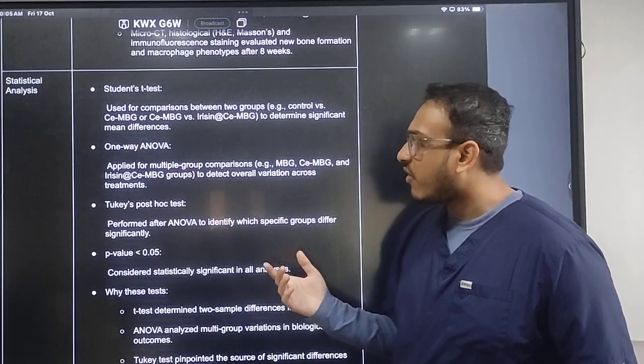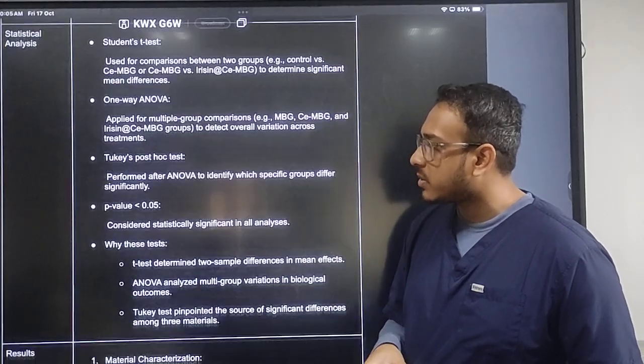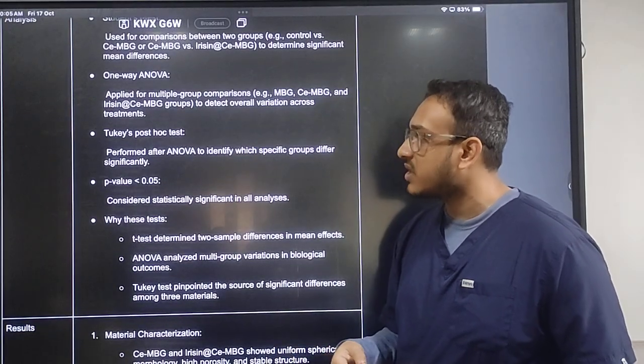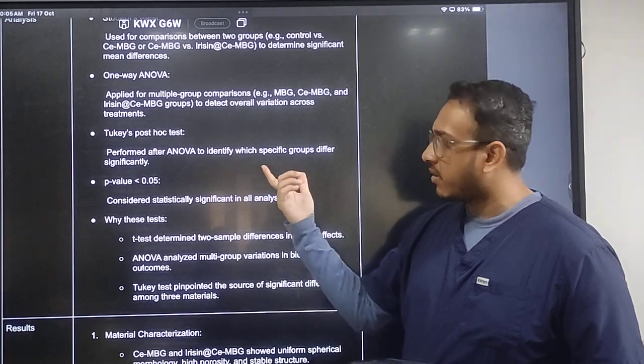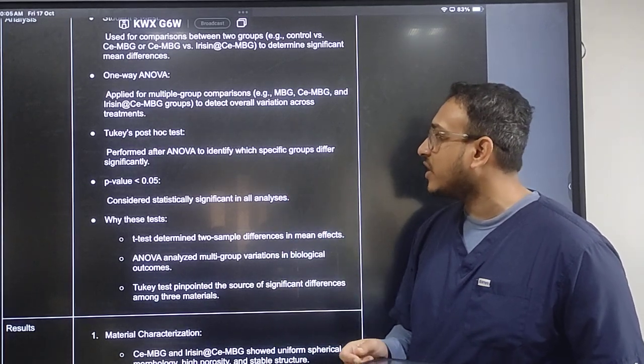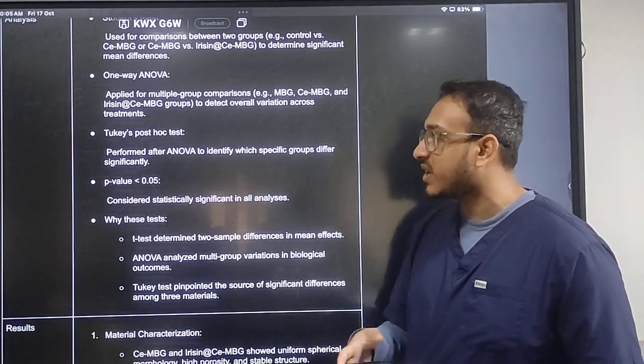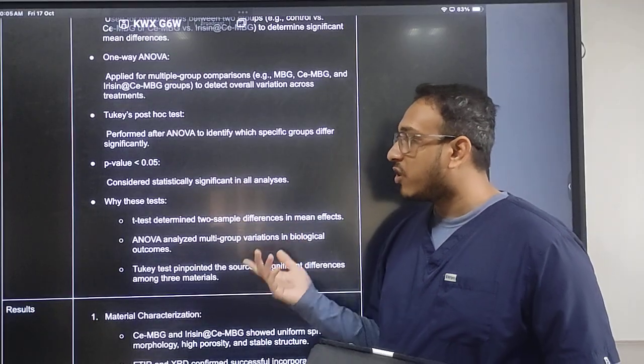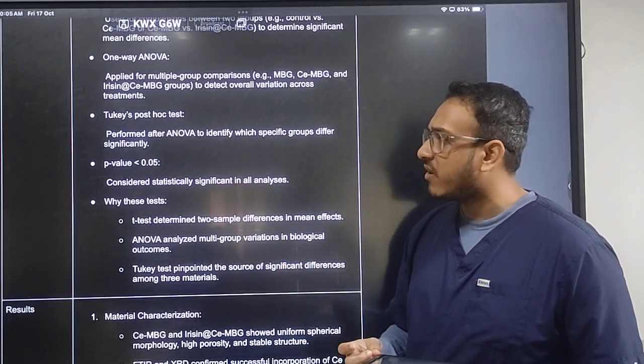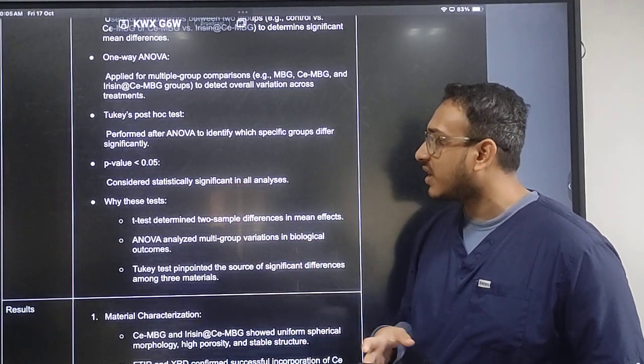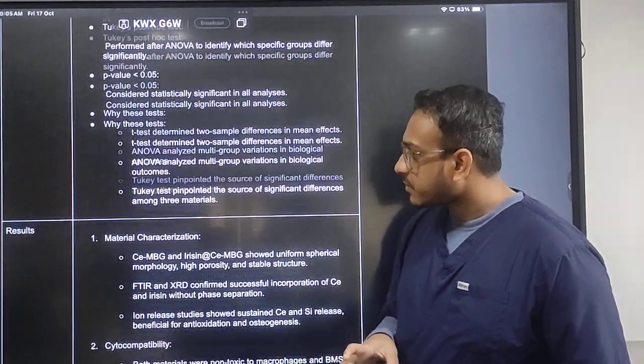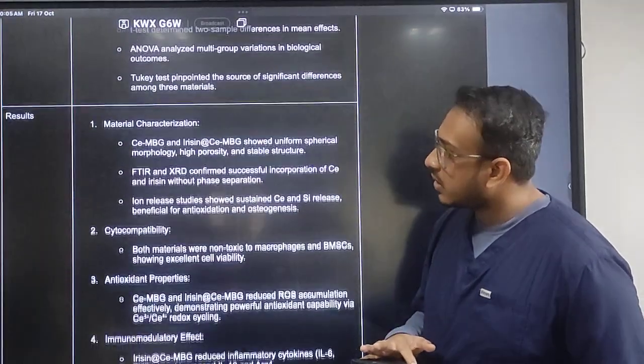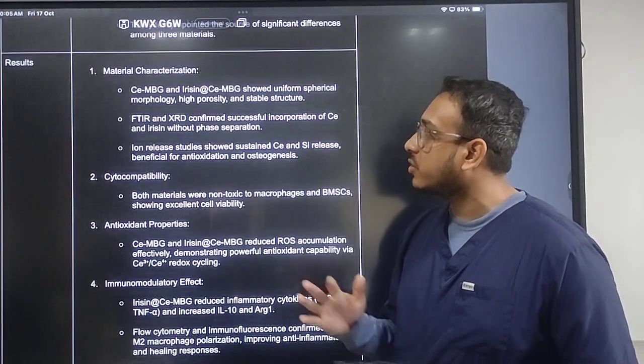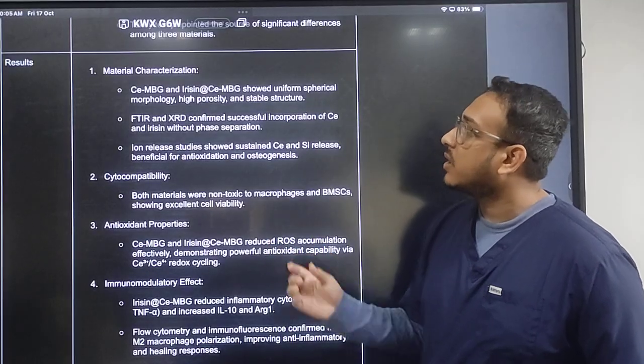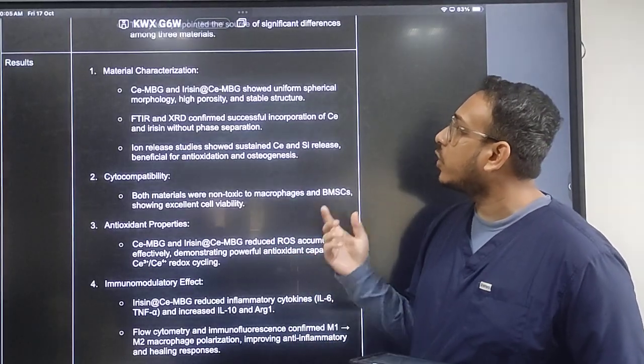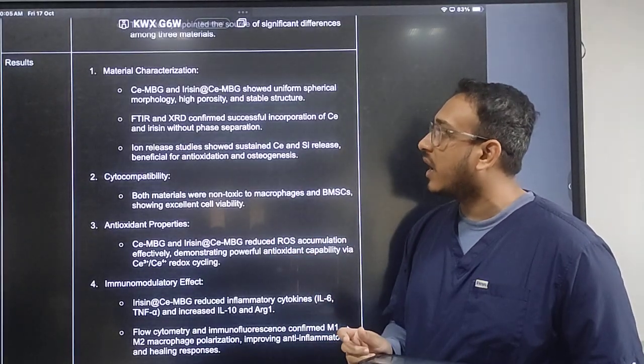the one-way ANOVA for comparison between multiple groups, and Tukey's post-hoc test, performed after ANOVA to identify which specific groups differ significantly. The p-value was set at less than 0.05, which was considered statistically significant in these tests. Then coming to the results, the material characterization: the material showed uniform spherical morphology and high